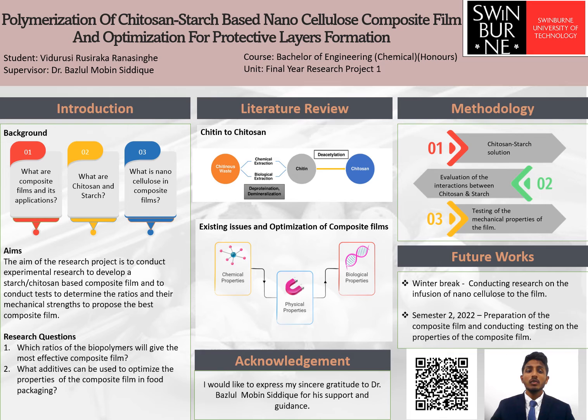When making the starch solution, I will be using regular starch, which is also known as 25% amylose cornstarch. Using this, I will be preparing starch solutions with 4 different concentrations: 1%, 2%, 3%, and 4%. This is done to test the effect of starch to chitosan ratios on the mechanical properties of the films. The starch is dispersed in distilled water, which is heated and stirred until the starch is gelatinized, and this temperature could range from 60 degrees Celsius to 95 degrees Celsius. After gelatinization, the solution can be cooled to 25 degrees Celsius.